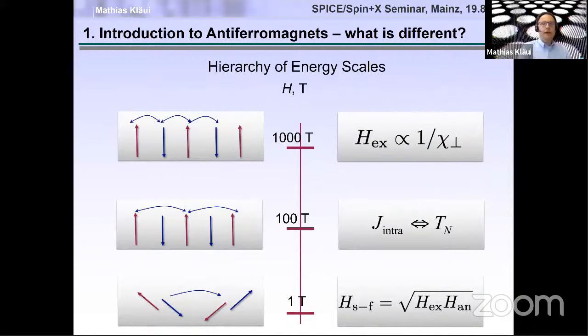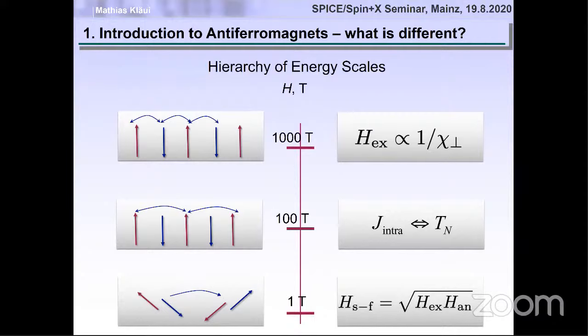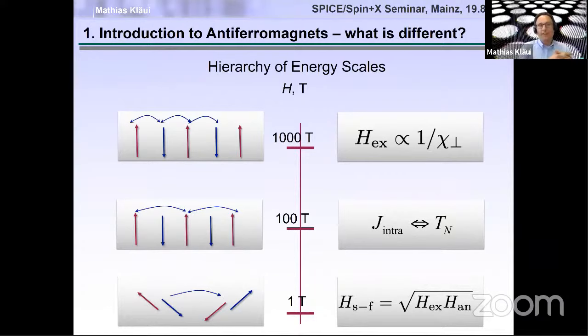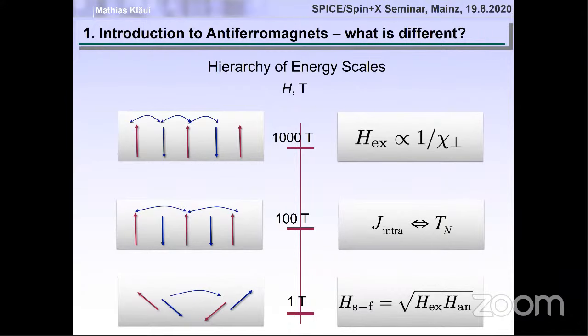Okay, so firstly, for the energy scales, the 1,000 Tesla is to bring the two sublattices from antiparallel to parallel alignment. So this sets essentially the transverse susceptibility. Of course, it depends on the materials, but for the ones that we are using, it's of that order. Of course, it's known that in layered antiferromagnets like chromium trichloride, this is smaller, so their field is not as large. But in typical ones like manganese gold or something like that, it's of that order of magnitude. Whether it's 500 or 5,000 doesn't matter. It's just much larger than anything we can do. Definitely. So the second question was concerning anisotropies.